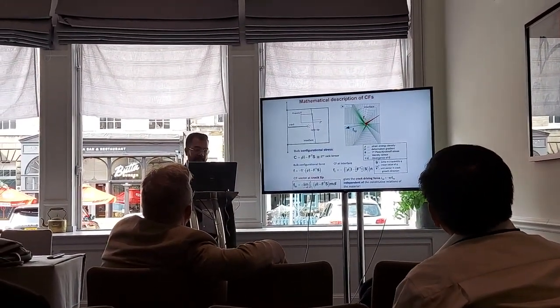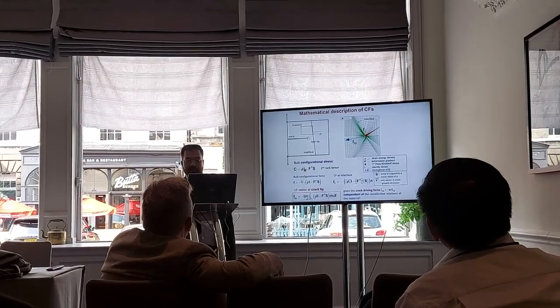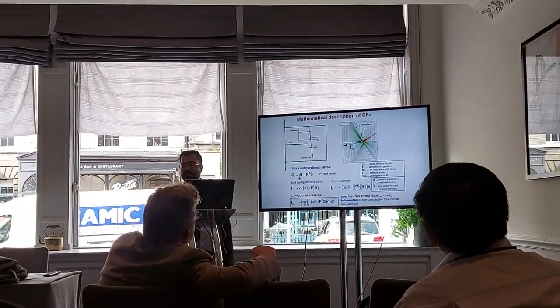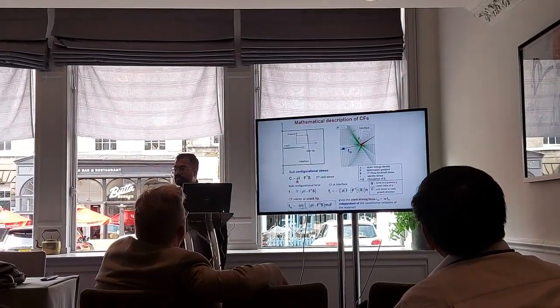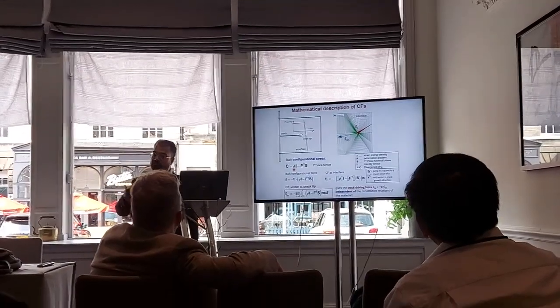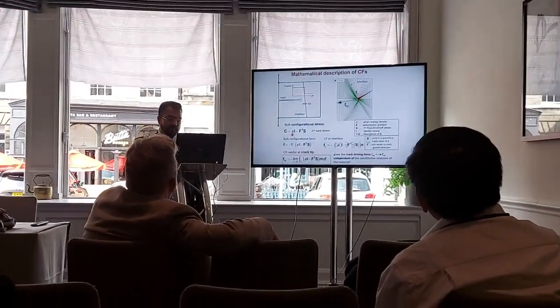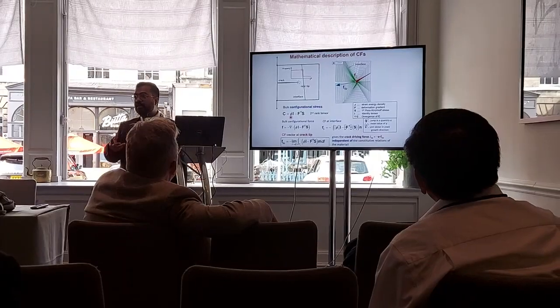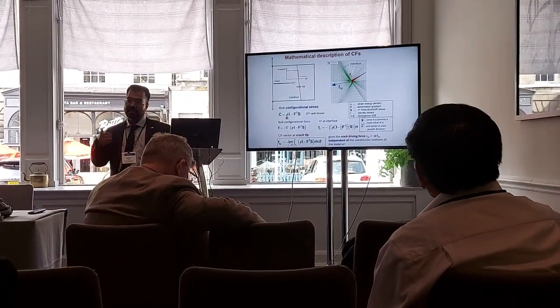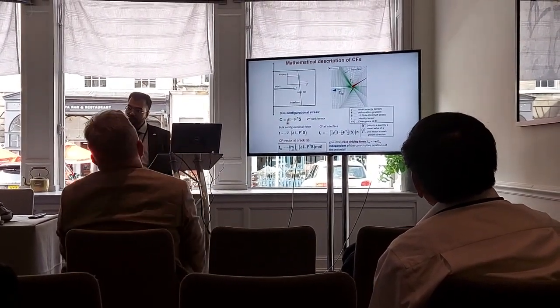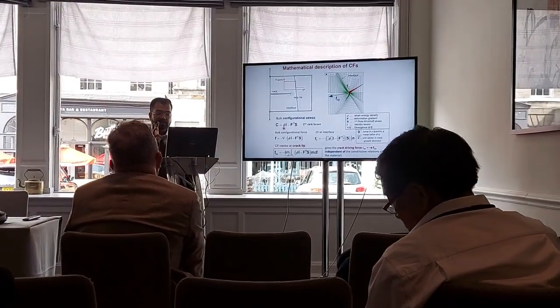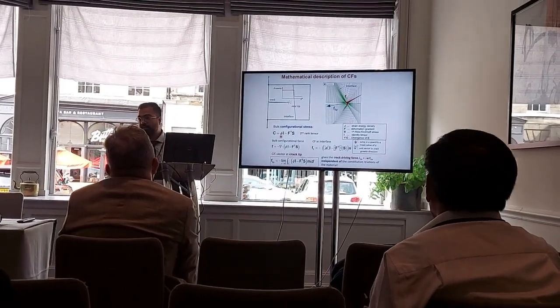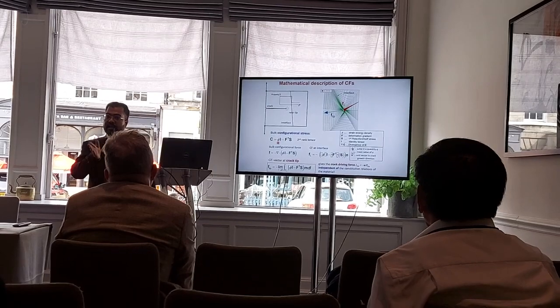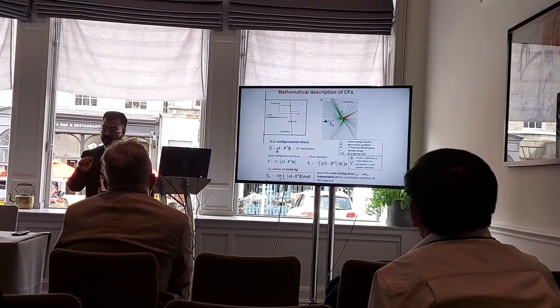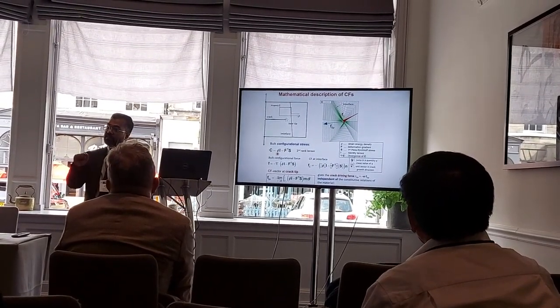The Eshelby energy momentum tensor, also known as the configurational stress tensor, is the strain energy density times the identity matrix minus the transpose of the deformation gradient times the first Piola-Kirchhoff stress. If you take the divergence of that, then you get the bulk configurational forces, and there is a negative sign. So we calculate the J integral by summing up these configurational forces in the direction of expected crack growth, and that makes the J integral a scalar value.